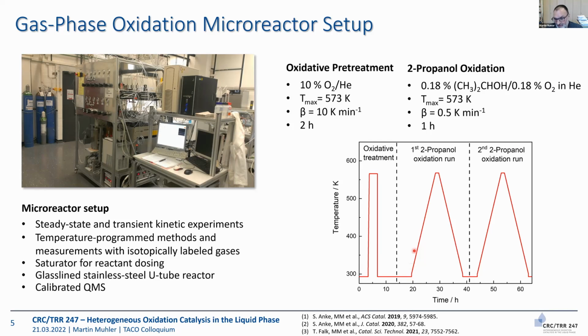And then we run a temperature ramp up and down. It's rather slow. You see time scale here is hours. And then we repeat the same experiment. It's a quasi-steady state experiment. That means we monitor conversion, selectivity when temperature goes up and down. And by repeating it, we check for reversibility. Heating ramp is then just 0.5 Kelvin per minute. That is like running quasi-steady state, many temperatures covered then in such a simple ramp experiment.